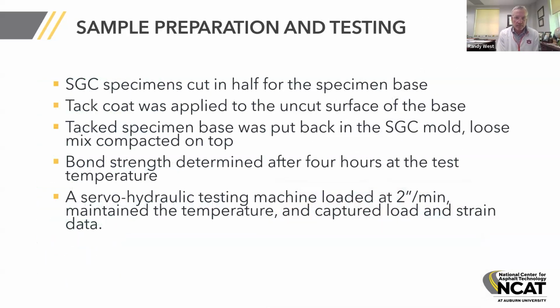The way we prepared the specimens, we first compacted the mix, the 19 millimeter or the 4.75 millimeter, in a gyratory. Then we cut it in half, and then we applied the tack material to the uncut surface. So the top and bottom, basically, we put the cut surface back into the gyratory mold. So we applied the tack coat to that uncut surface, put that cut specimen back into the gyratory mold. We put loose mix on top of it, compacted the mix, and then later determined the bond strength.